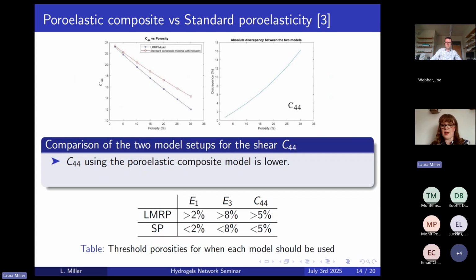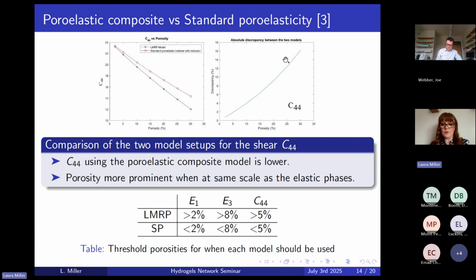And I had done the same for C44. So I have, again, we can see that using our model, it's lower than the standard approach. And again, I've plotted the discrepancy. And again, you can see that at 30%, we're reaching up to 16, 17% discrepancy between the models.